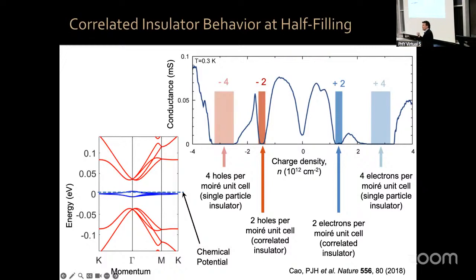What has happened here is that a correlated insulator, an insulating state due to interactions between electrons and holes in the system, has appeared. So this was the first surprise that we found. How come this system becomes an insulator when it should be a very good metal? It has to do again with this correlated insulating behavior.